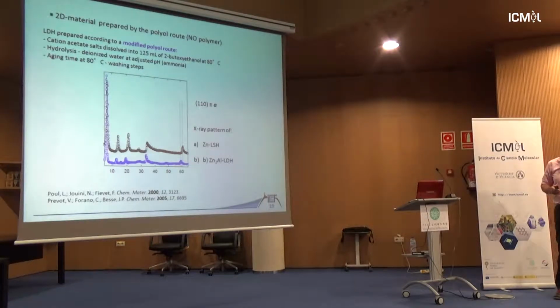If we do the experiment with no polymer, it shows what is reported in the literature. So you have the zinc aluminium LDH here, and the peak here is the 110, directly related to the cell parameter. So it's a mixture of cationic radii of zinc and aluminium. And you have the zinc LSH, layered single hydroxide, here. It's small, but it's significant.